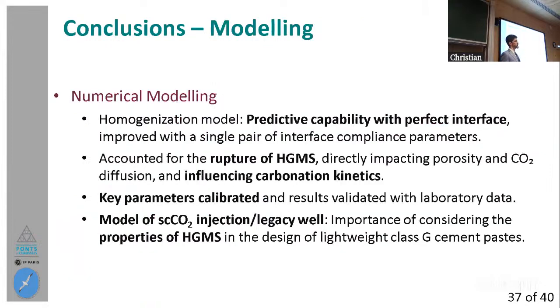In the modeling parts, we have obtained within a modified homogenization model a good predictive capability with a perfect interface already, but we were able to improve it a bit. We get errors that were even lower than 5% in absolute value. We were able to account for the rupture of the spheres, which affected both the interconnected porosity and the diffusivity of the CO2 in the cement matrix. We were able to calibrate some key parameters to obtain the results obtained in the lab.